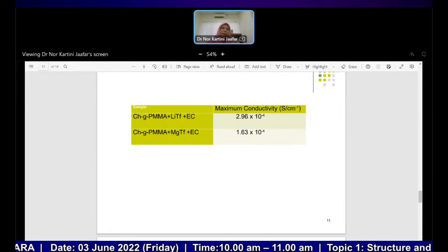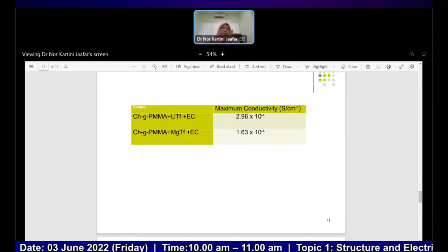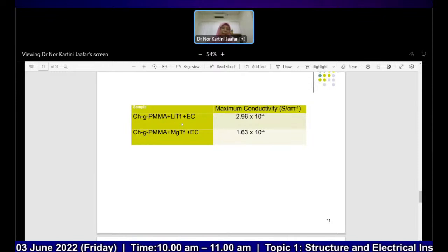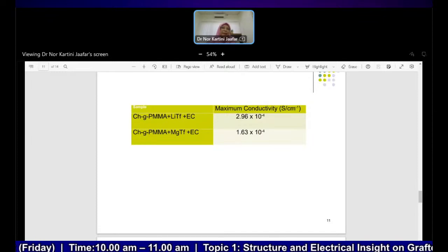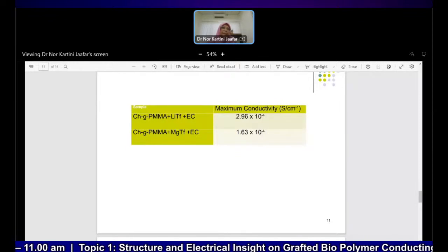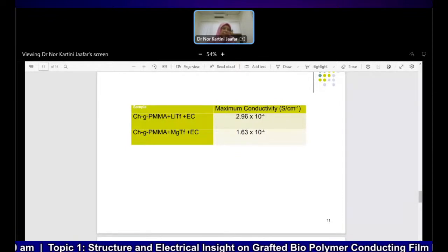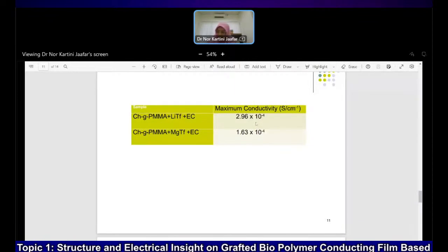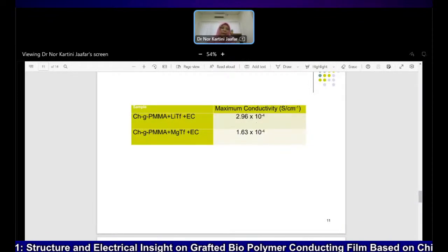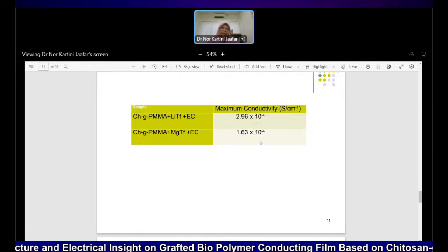Actually, without plasticizer, the lithium system has higher conductivity compared to the magnesium system. But when we use the plasticizer, we can show that actually the magnesium system can also enhance the conductivity, within power of -4 Siemens per centimeter.